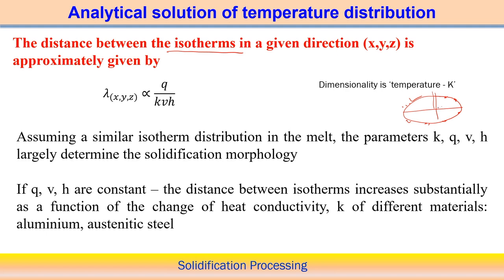So if I assume this is the profile of a mold, suppose this is the melting point, or its solidus temperature or liquidus temperature. This is represented by one spatial distribution of the temperature, and that is called the isotherm. The isotherm can also be like this, and that isotherm can be a different temperature which is less than the melting point temperature, some solid state phase transformation temperature we can consider, and that is represented by the isotherm. That is why you can easily find the different isotherms by solving this heat